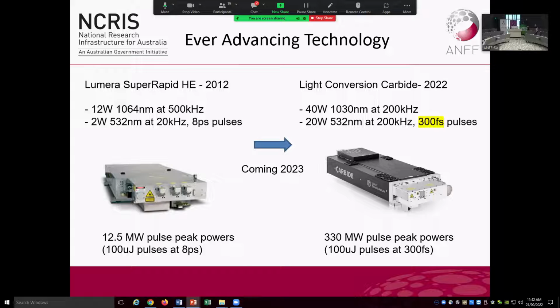So what we're going to be looking at doing next year is upgrading our old picosecond Lumera laser, which gave about 8 picosecond pulses, to a new class of lasers which have become mature in the last few years, which are femtosecond lasers that can scale up to 20 or 40 watts. Now, 20 or 40 watts may not sound very large when we're talking about kilowatt fibre laser cutters. The thing is the peak pulse energy. For 8 picosecond pulses, we're talking each individual pulse might have a peak power of 12.5 megawatts.